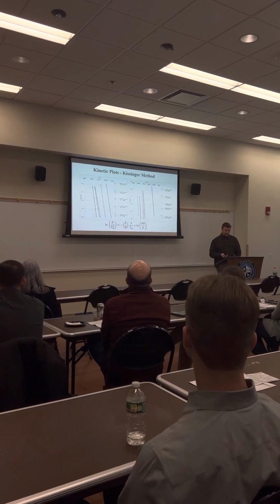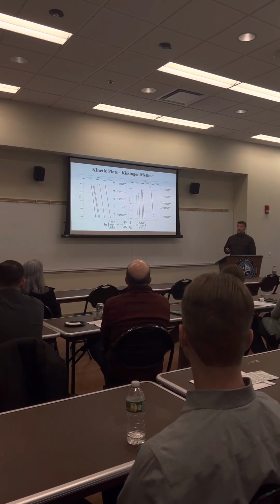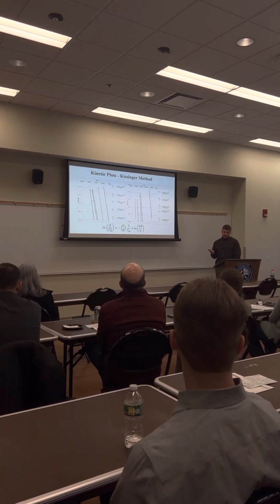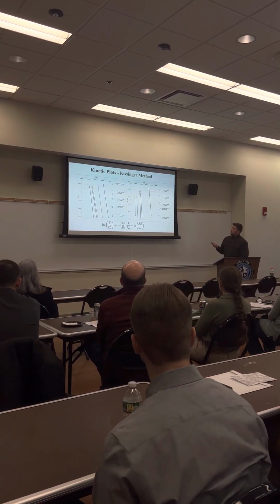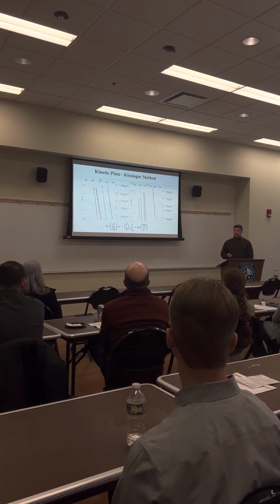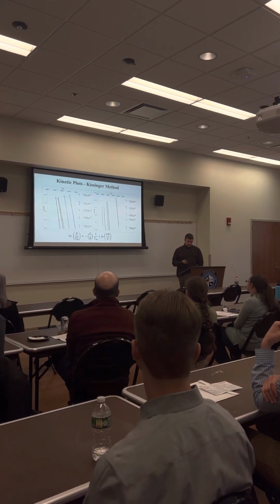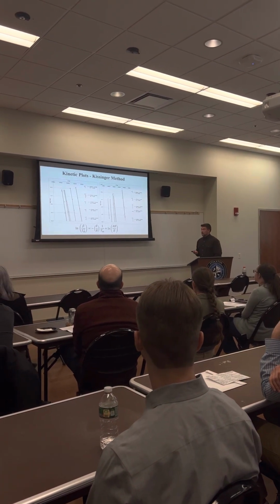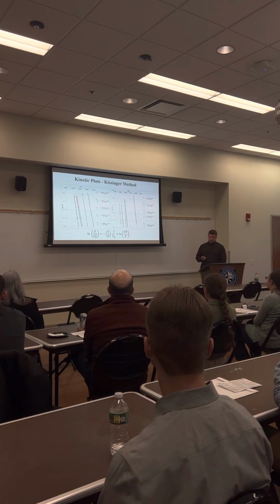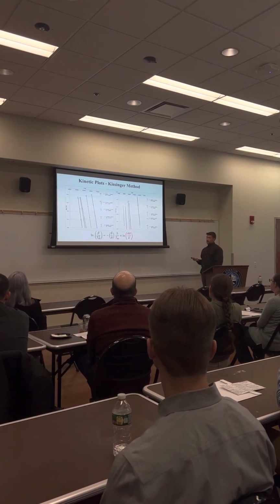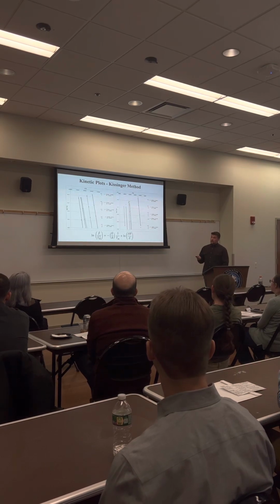So the first mathematical method we applied was the Kissinger method. This is usually the go-to method in this type of analysis, and when you take the y-intercept, the y-intercept gives a frequency factor for each. These are all the materials plotted. So at the y-intercept, you have your frequency factor, or your exponential factor. In order to get the activation energy, you use the slope from this equation. You take the slope and multiply it by the gas constant and then divide it by 1000, and you end up with the two kinetic parameters that we were looking for from the start.